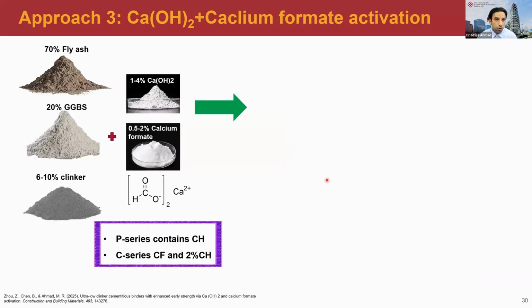And so another approach to how we can reduce the clinker in the cementitious material. This is the third approach. This is our most radical and very ambitious approach, because we just wanted to know what is the absolute minimum amount of clinker we need to trigger the reaction. So we aimed for a very ultra low clinker cement, and in this we used 70% fly ash, 20% GGBS, and 6 to 10% clinker, which is an extremely low clinker content. And here we prepared two sets of mixtures.